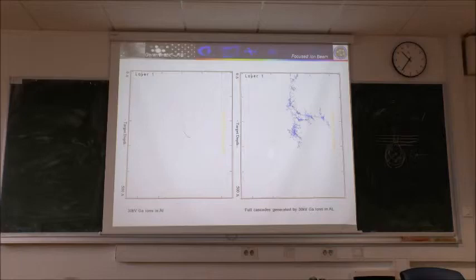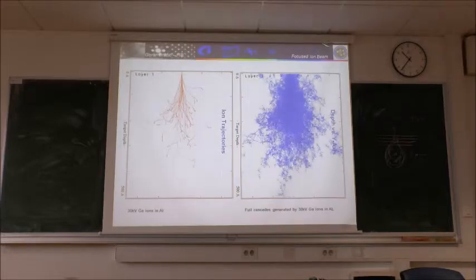These are some Monte Carlo calculations of one trajectory of just one gallium atom. It goes from the surface up to here, which is something like 20-25 nanometers. And these are the complete cascade, so not just the gallium, but also the intrinsic material, the intrinsic ions that are inside. If you multiply this by, I don't know, a few tens, 100 for instance, we see that the estimated volume where our information comes from, or where we damage our material, is still somewhere in the order of 20, 30, 50 nanometers. It's not so bad.